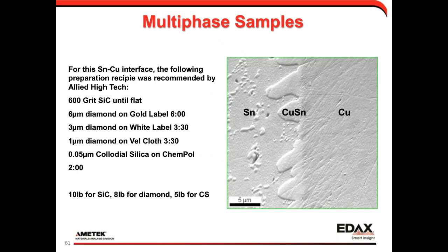It's a solder sample, so you have a tin and copper interface. For this case, I asked Allied High-Tech what they'd recommend. They came up with a specific recipe that's shown here with specific abrasives, specific cloths, specific times and pressures. What they're able to do here is target specific approaches that should, in this case, minimize deformation and make it as flat as possible for these materials that are different hardnesses.